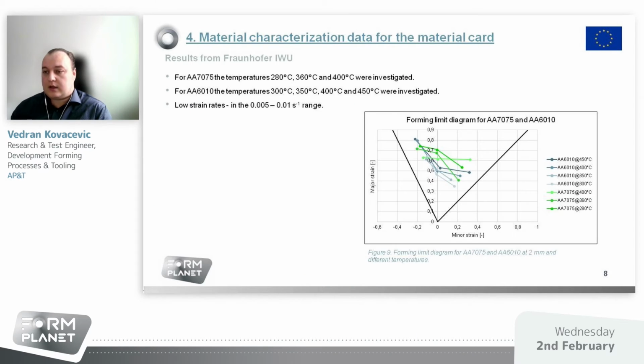In addition to the hot tensile tests, Fraunhofer also performed hot tensile tests in 3 different load states to describe the forming limit characteristics of the alloys. This was done for uniaxial strain, plane strain, and biaxial strain. Unfortunately, due to equipment restrictions, the strain rate used during these laboratory tests for the 7000 alloy was very low. And as will be shown in the results later, this does not reflect the real strain in the material behavior for this hot stamping application.